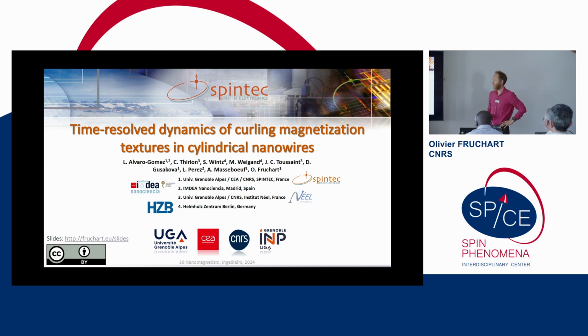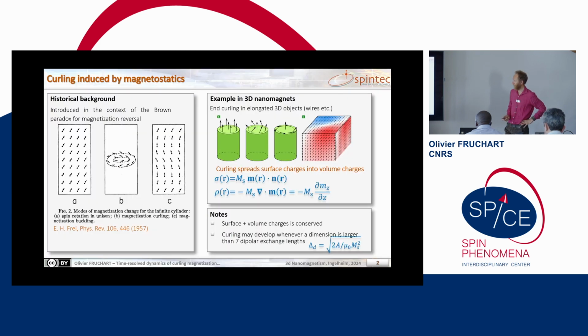So today I will present time-resolved dynamics of magnetization textures with curling of magnetization. So what is curling, if you don't know? It is the tendency of magnetization distributions to close their flux due to magnetostatics. And it is a very old concept introduced originally to explain the Brown paradox, why coercivity may be much lower than the anisotropy field in large magnetic systems.